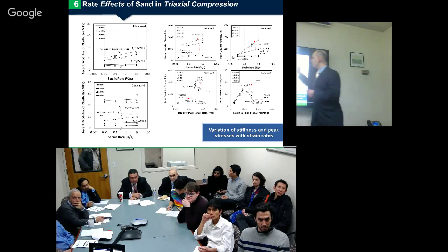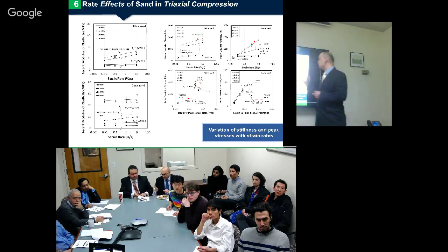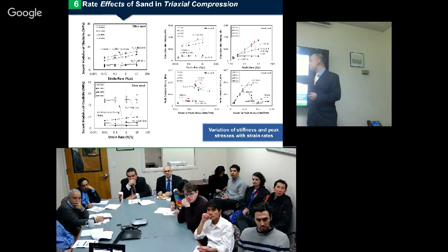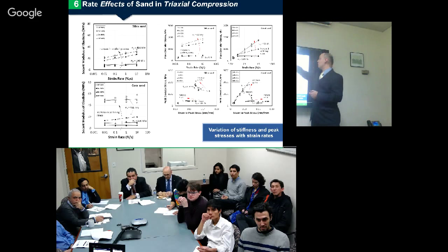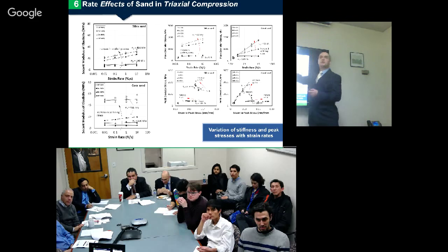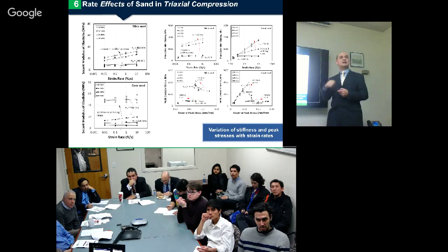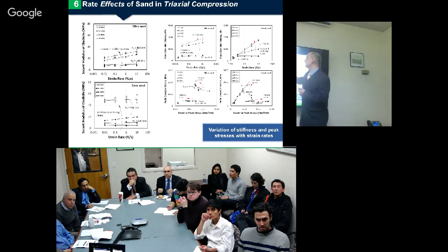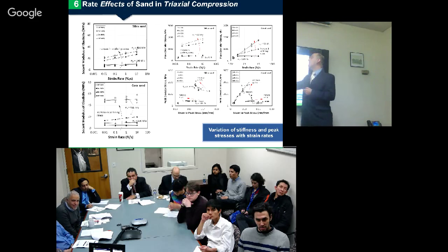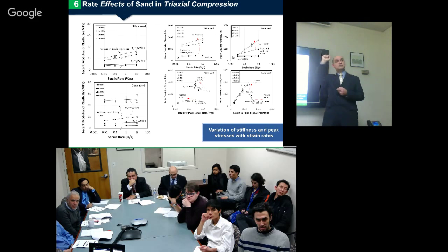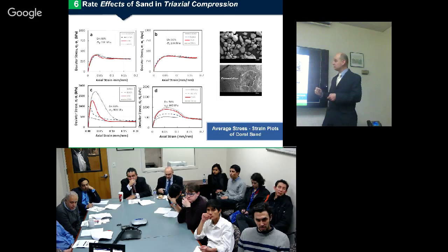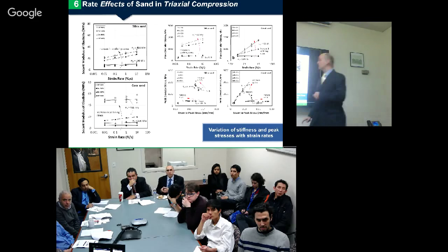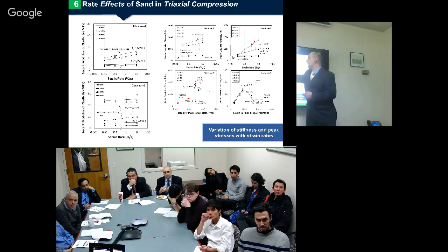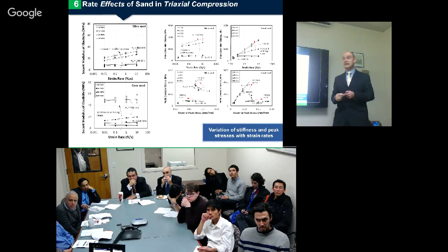Now, in these four main pictures, we can see the big deviator stress in all conditions. Here we have a strain rate for silica sand and coral sand for two different confining stresses, and we can also see that the peak deviator stress, so the maximum, the final strength at the end, so this peak, is also moving as the strain rate is being increased.